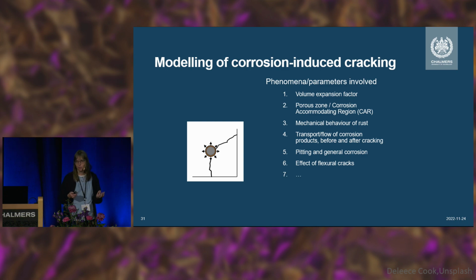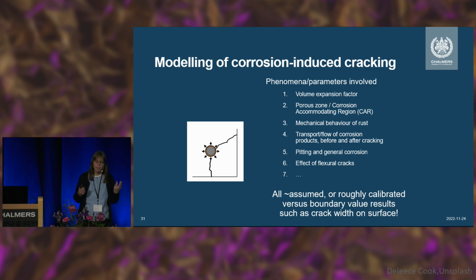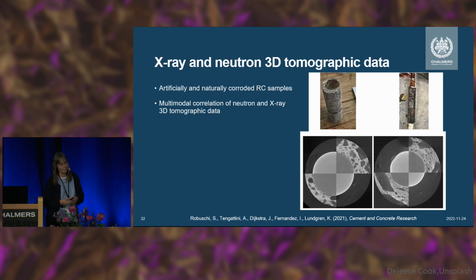I started working with this roughly 20 years ago, and you can do this. I modeled this. But what I did, and what everyone else has done, is to calibrate models just based on what we can see on the outside. So all we actually have is corroded specimens, where we measured the crack width, and then we broke them and saw how much corrosion we had on the inside. But that really limits us, because it means we need to guess so many values that you can calibrate it in many, many different ways. Too much uncertainty involved, so to say.